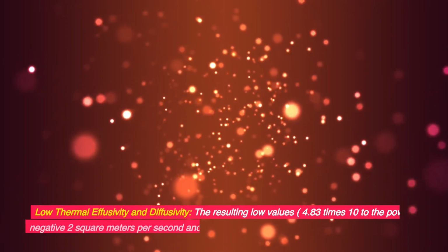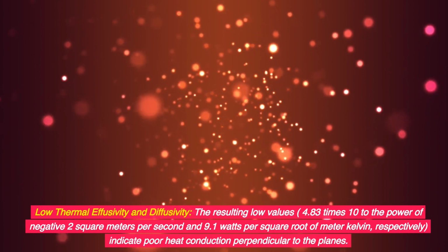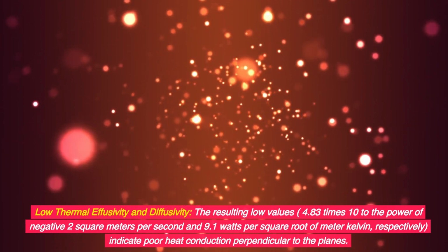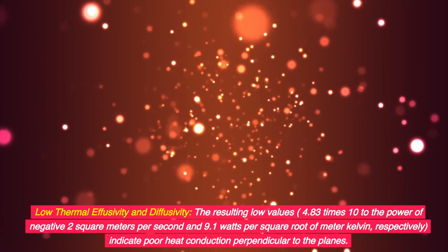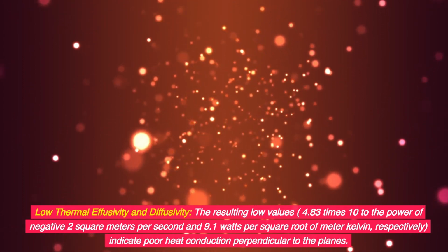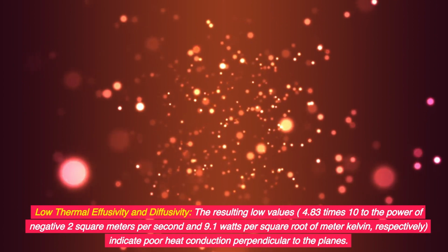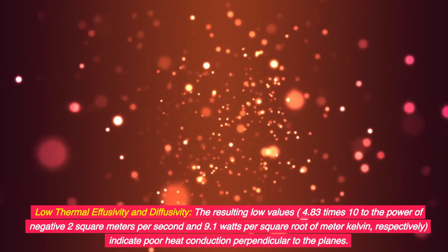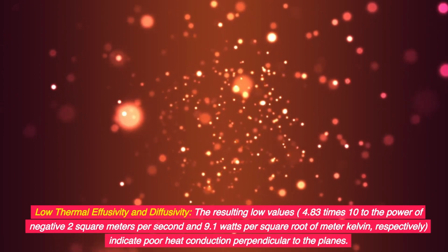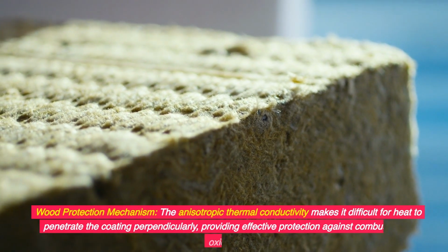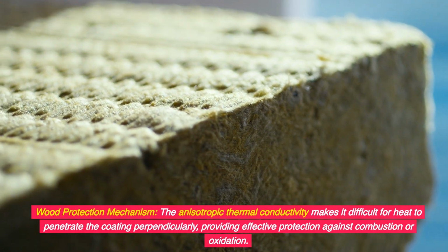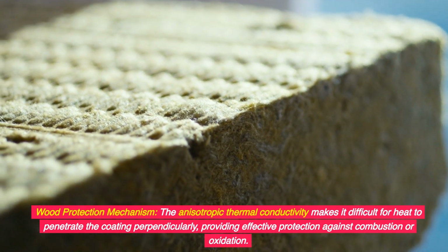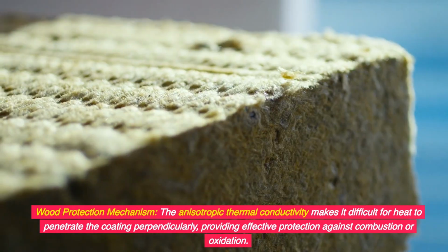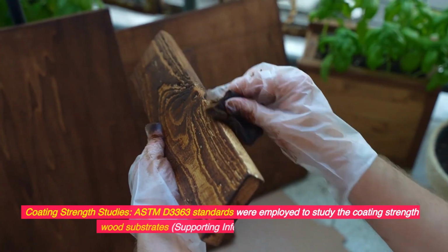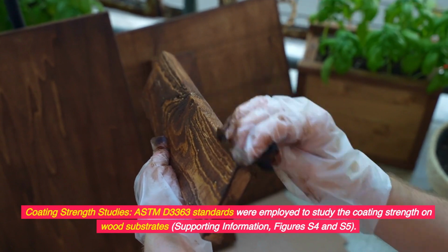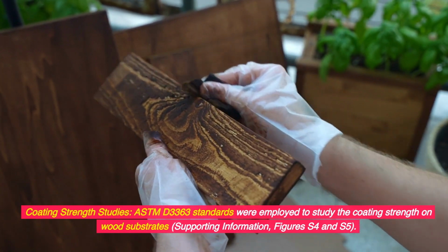Low thermal effusivity and diffusivity. The resulting low values, 4.83 times 10 to the power of -2 square meters per second and 9.1 watts per square root of meter Kelvin, respectively, indicate poor heat conduction perpendicular to the planes. Wood protection mechanism: the anisotropic thermal conductivity makes it difficult for heat to penetrate the coating perpendicularly, providing effective protection against combustion or oxidation. Coating strength studies: ASTM D3363 standards were employed to study the coating strength on wood substrates,